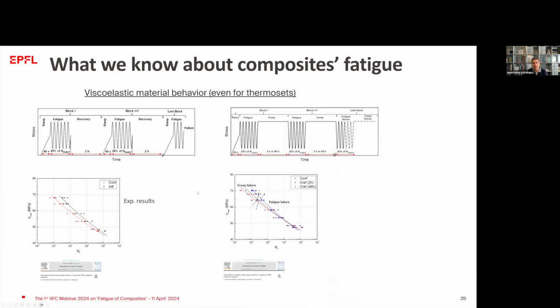We did the same also doing the opposite, keeping the loading at a high stress, so introducing creep, and we introduced creep for 2 hours and 48 hours. And the effects are shown also here in this graph. The continuous loading is the black curve in the middle. And what we've seen here, which is quite interesting, is that when we stop the test only at 2 hours and introduce a very short creep component, we see an increase of the lifetime, which means that this short stop actually helped the material recover instead of making the behavior worse.